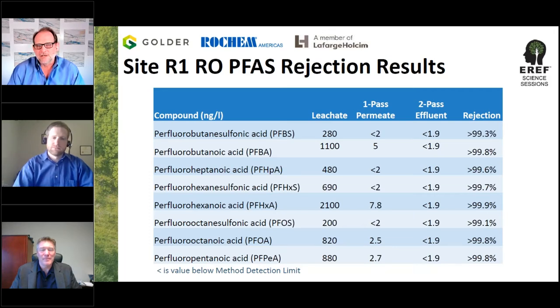We actually did the full scan of 37 PFAS compounds. These were the ones that were above 100 parts per trillion in the leachate. There were about another 8 or 10 that were between detection limits and 100 parts per trillion, and then about 15 or 20 that were effectively not detected in this specific leachate. Through the first pass, we took thousands of parts per trillion down to single digit parts per trillion on all the compounds. And after the second pass effluent, none of it was detectable above the detection limit that was available at that time when we did these samples. So it works very well.